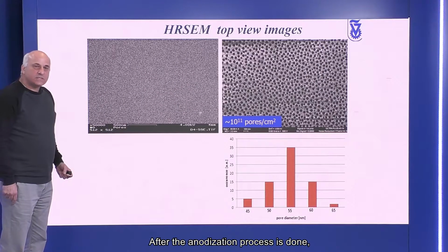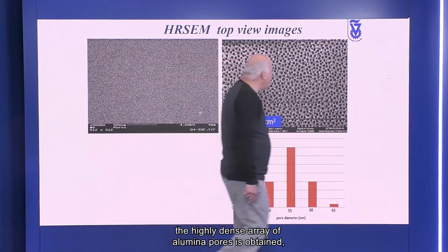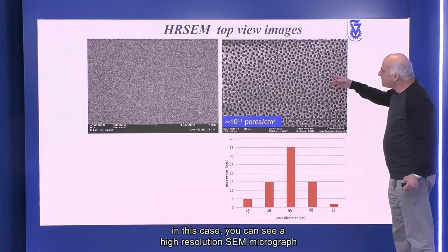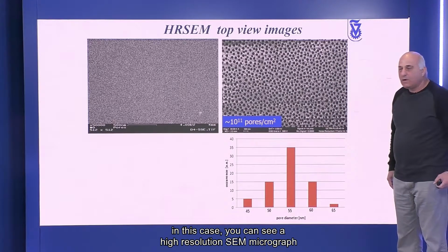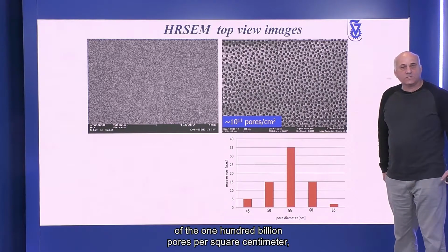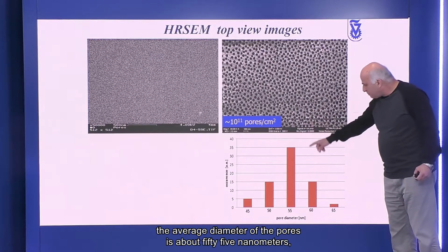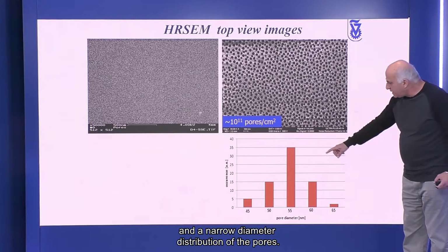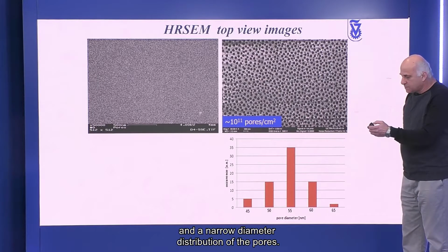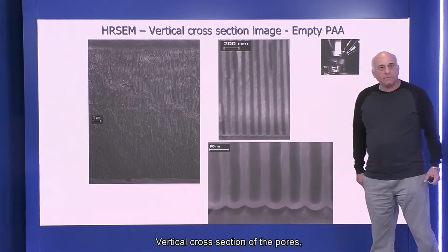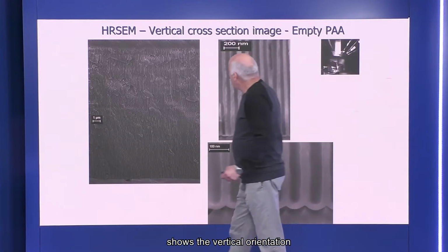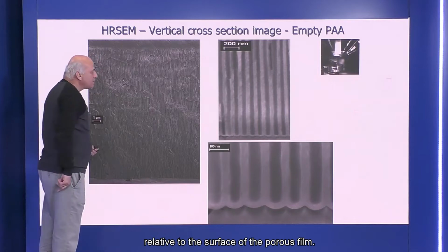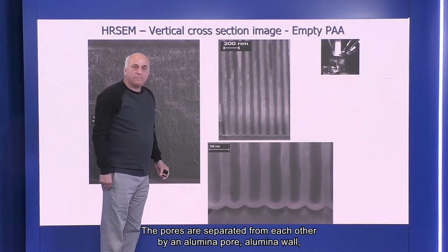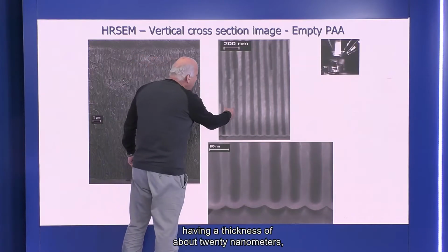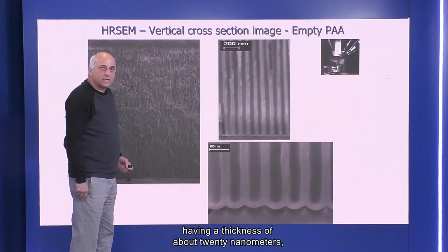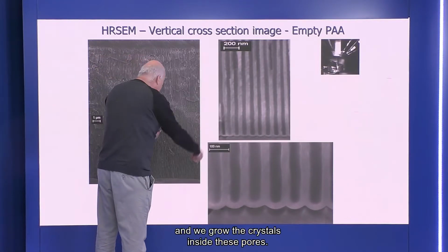After the anodization process is done, a highly dense array of alumina pores is obtained. In this case, you can see a high-resolution SEM micrograph of the 100 billion pores per square centimeter. The average diameter of the pore is about 55 nanometers, with a narrow diameter distribution. Vertical cross-section of the pores shows the vertical orientation relative to the surface of the porous film. The pores are separated from each other by an alumina wall having a thickness of about 20 nanometers, and we grow the crystals inside these pores.